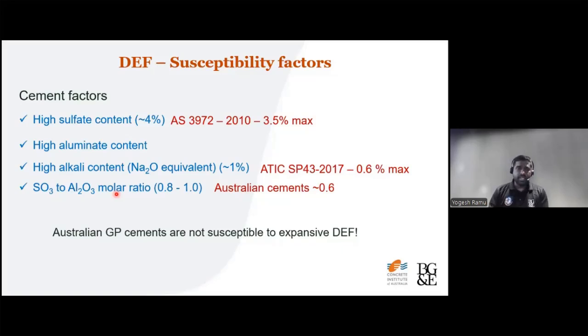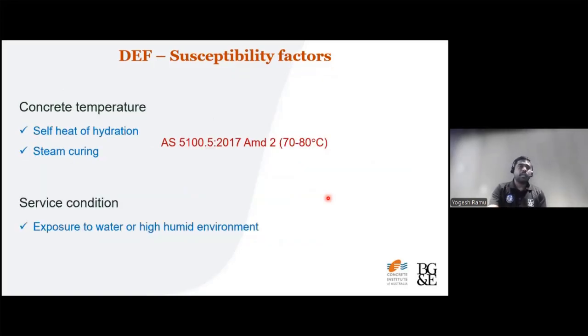Luckily, Australian standards are actually pretty good. They restrict the sulfates to 3.5, and the alkali levels are restricted to 0.6. Typically, Australian cements have about 0.6 sulfate to aluminate molar ratio, which is below the levels required to have highly expansive DEF. So from a cement chemistry perspective, Australian cements are not that susceptible to expansive DEF, but it's not the only factor that can lead to DEF.